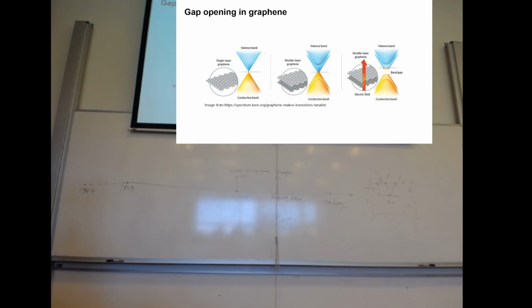The semi-metal has a dispersion where at the Dirac point you have a minimum of density of states. That's why you have a peak of resistance. And experimentalists and theorists don't give up. They say there might be some ways to induce gaps in graphene. For example, a good example is that in bilayer graphene, if you induce a vertical electrical field, then there will be a band gap opening there.